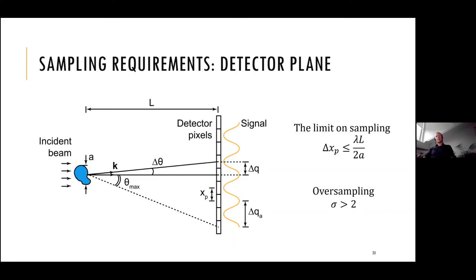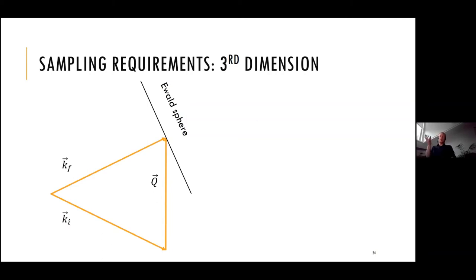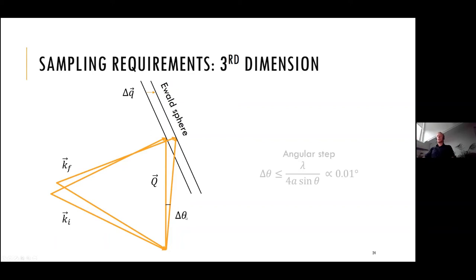But in the case of Bragg CDI, you also have a third dimension. So how do you sample the third dimension, because you actually record by doing rocking curves. So this is how the initial state looks like for the first position along the rocking curve. The second one is basically a rotation of this triangle by some small angle delta theta. And you can see that the sphere, with an approximation of very small angles, just moves along this coordinate delta q. And this delta q is related to delta theta almost directly with this relation, where delta theta should be proportional to the inverse of object size. So the larger the object you have, the smaller the step in the Q space should be, and vice versa. This number is just an order of magnitude of the angular step for an average experiment. So it's hundredths of degrees. That's the precision you need for your scanning stage.